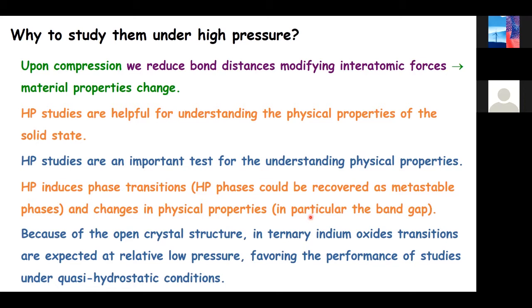One of the properties that will be strongly affected will be the band gap. Then, because of the open crystal structure of many of these ternary indium oxides, phase transitions were expected to happen at relatively low pressure. By relatively low pressure, I mean below 10 GPa. So 10 GPa is 100,000 atmospheres, but for those working in high pressure research, that's a very low pressure. The importance that the transition happens at these very low pressures is that they favor the possibility to study these compounds under nearly hydrostatic conditions. This means that all the changes we are inducing in the material, we can assume they are just induced by pressure and not by other stresses like deviatoric stresses.